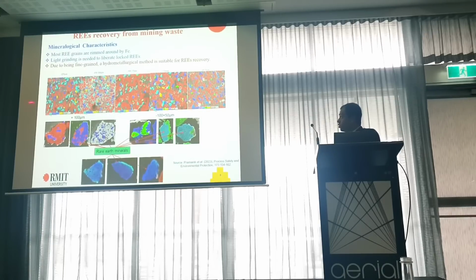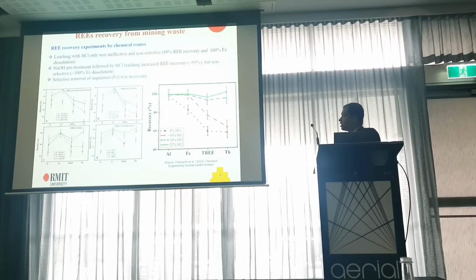As we said, most rare earth element grains are mixed with iron. Looking at these mineralogical characteristics, and because of the fine grain, less than 61 microns in more than 50% of the sample, we thought a hydrometallurgical route could be a good way to recover the rare earth elements. We tried leaching with hydrochloric acid, but it was not effective and non-selective: 89% rare earth recovery, but 100% iron dissolution. Then we used sodium hydroxide followed by